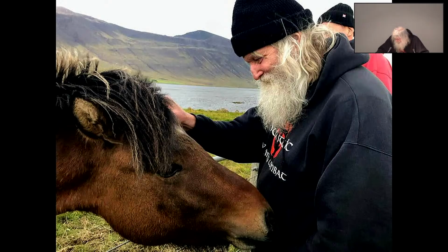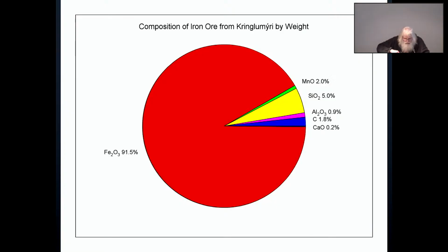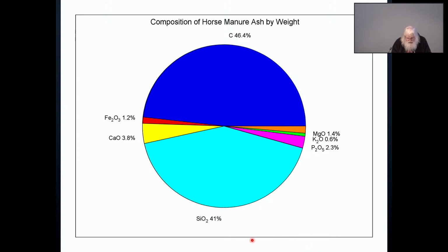So it wasn't unknown. And so our experiments were to look at all these materials and do some tests and try to figure out what the quality of the iron might be. So our hypothesis was that it was possible to make iron here in Iceland, good quality iron, using all Icelandic materials and using horse manure ash as the refractory material. So we start with testing. First of all, we do elemental analyses of the iron ore available. And the iron ore available is excellent. So it's very high percentage of iron. The impurities are a small percentage, and importantly, none of the impurities are anything that is going to poison the process, to hurt the process. Next, we looked at the horse manure ash that was created here in Iceland, and there's a lot of silica in it, so this looked very, very promising.